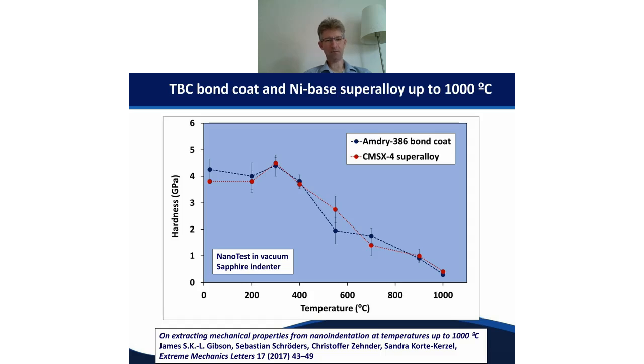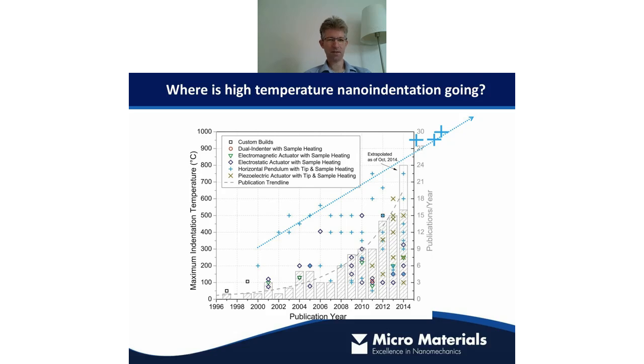And you can pull out mechanical properties as a function of temperature on these things. So as I say, the hardness stays reasonably constant and then drops dramatically. And you can see this bond coat particularly, it's dropping more rapidly here than the superalloy. And this is the sort of thing that people need to understand to optimize their material behavior. So high temperature testing is getting to higher and higher temperatures since our customers are producing more and more data at these very high temperatures.